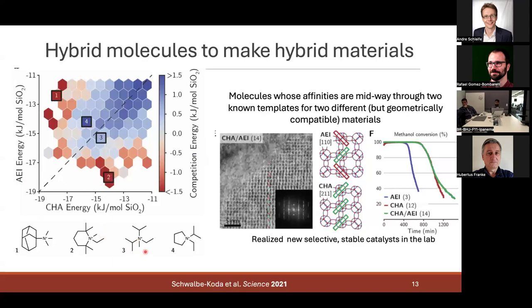So our colleagues were able to navigate the design space we had set to find these couple of molecules that are on the diagonal, right? They're pretty good for chabazite and they're pretty good for AEI. And when you put this in a reactor, what you get is what's called an integrowth, a single crystal that is a random mixture of the two orientations of planes that differentiate AEI and chabazite. So we were able to make this controlled intergrowth whose catalytic properties were, as suspected, halfway between the more expensive AEI and the cheaper chabazite.